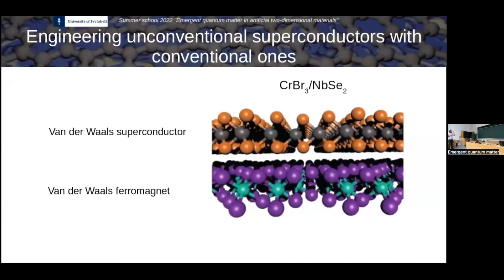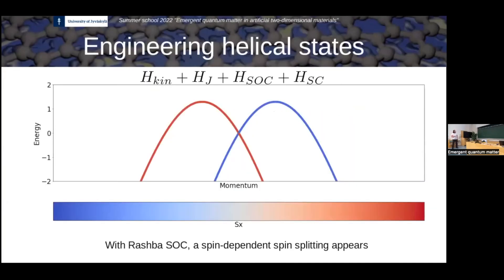As a reference, let us think that we take first a van der Waals ferromagnet — any system with out-of-plane magnetization, such as chromium tribromide, chromium triiodide, or many other out-of-plane ferromagnets in the van der Waals world. Then we take a conventional two-dimensional superconductor — it can be niobium diselenide, tantalum disulfide, niobium sulfide, or any other superconductor. We just create a heterostructure: superconductor and ferromagnet. The basic idea is that we are going to slowly switch on every single ingredient of the Hamiltonian that this system has.